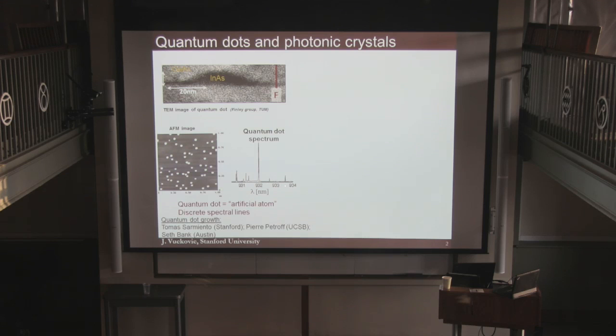But also in the bottom left, you see that there is a discrepancy in the sizes and shapes of these quantum dots, which leads to variation in the quantum boxes that confine carriers, and that leads to a discrepancy in transitions, or inhomogeneous broadening. So we have these artificial atoms, quantum emitters that have narrow spectral lines in this range, but also all quantum dots are different from each other, so we have to worry about tuning them onto resonances and onto each other.